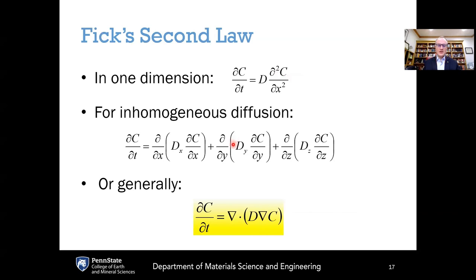Another way that you could write Fick's second law to account for inhomogeneous diffusion, if you've got different diffusivities along the x, the y, and the z direction, in that case, if all three of those numbers are different, then it's no longer a common factor to be pulled out in front, but those x, y, and z diffusion coefficients would then be multiplied by this first partial derivative with the second partial operator outside of that.